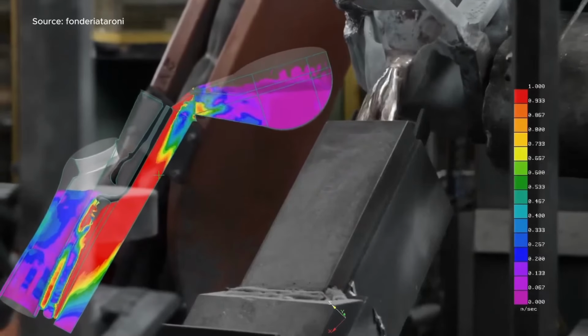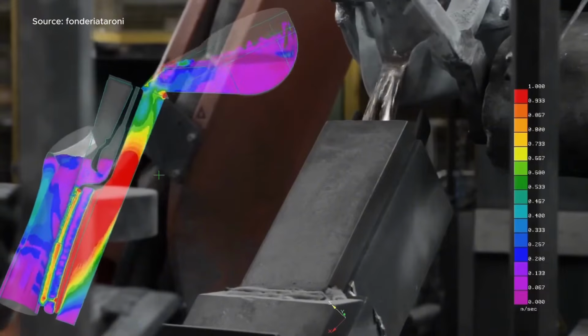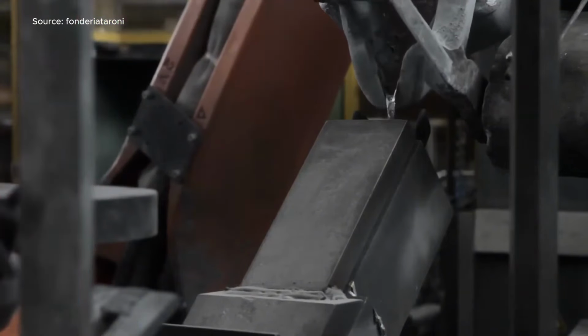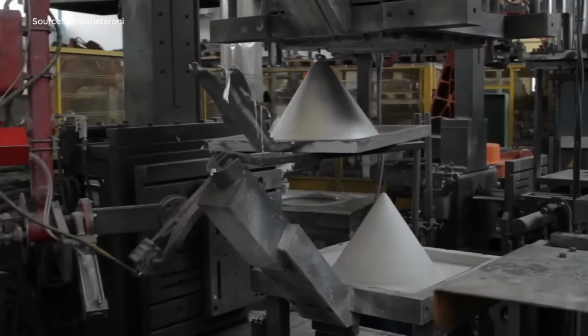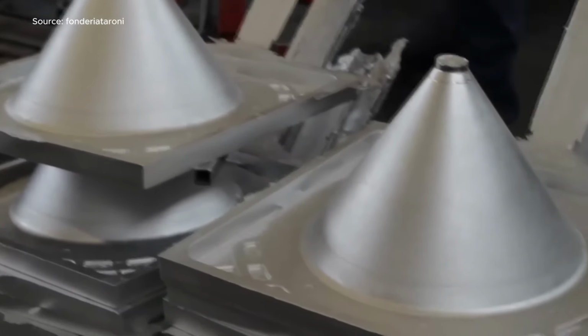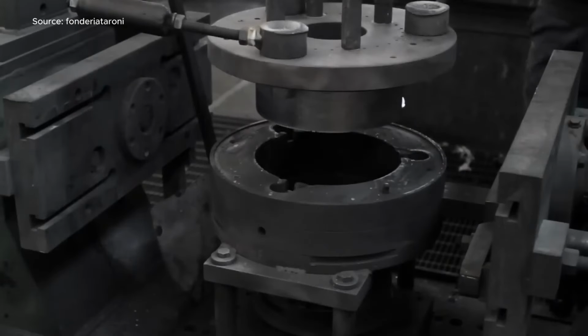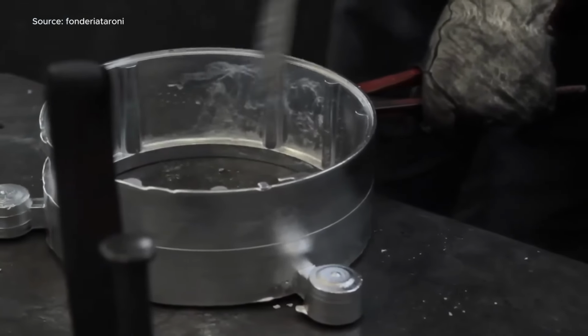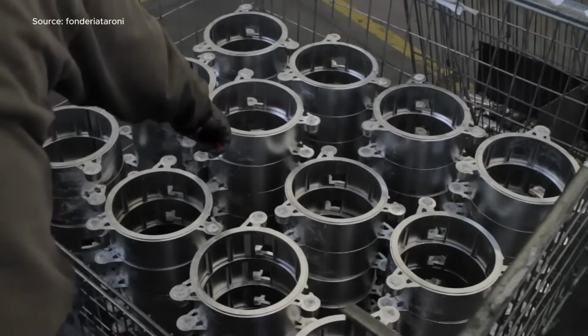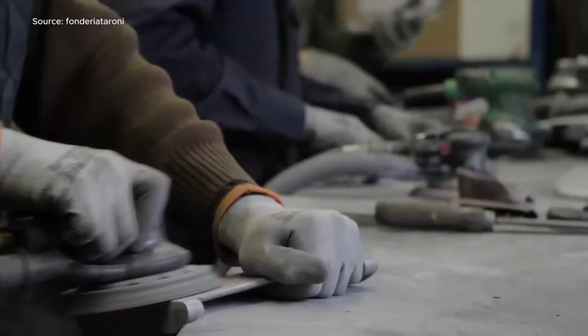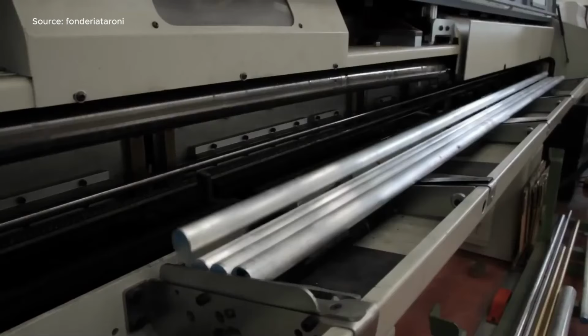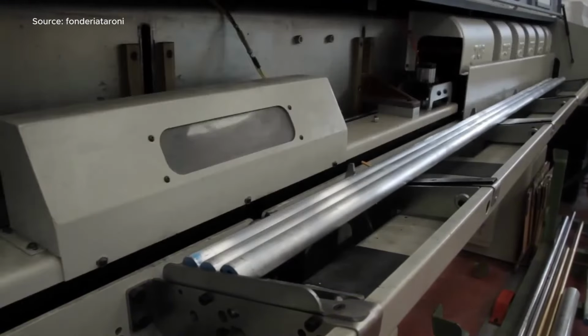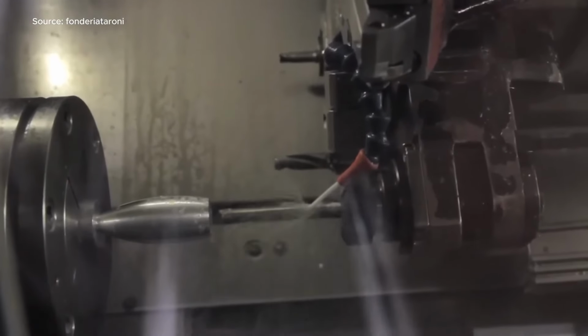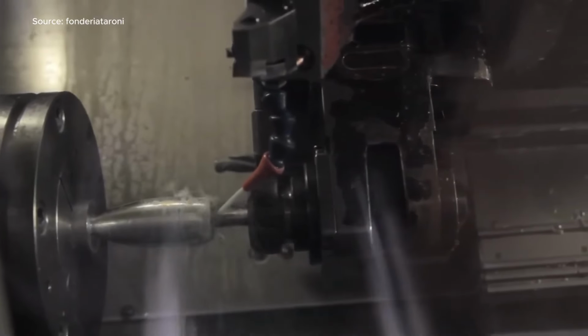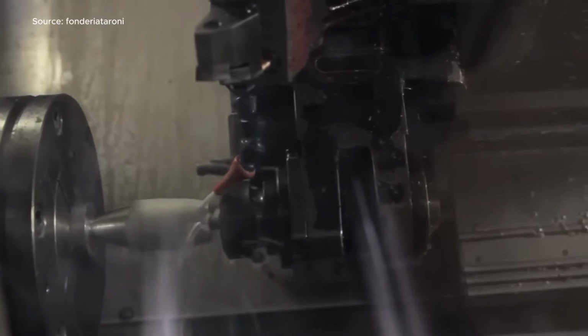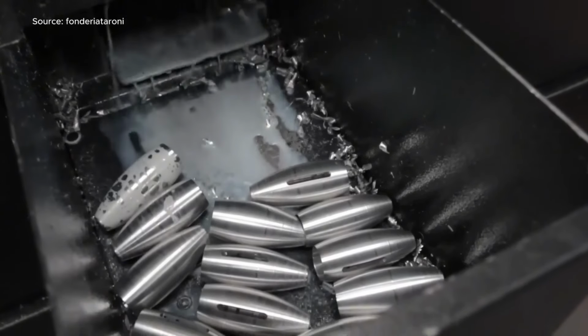Following machining, the castings undergo heat treatment at 400 degrees Celsius for up to 4 hours to enhance strength and reduce residual stresses. Surface finishing is applied, with anodizing layers typically ranging from 15 to 25 microns to improve corrosion resistance. Finally, quality control is ensured through 100% inspection, using X-ray machines and coordinate measuring machines, CMM, to check critical dimensions. This streamlined process guarantees high precision and reliability in aluminum castings for diverse industries.